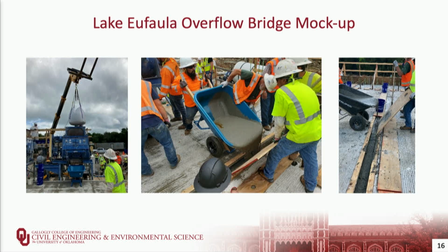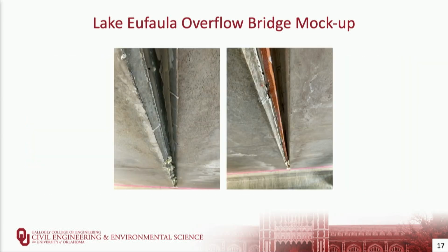For the mock-up, they used 2 horizontal axis high shear mixers and a proprietary UHPC material. They placed the UHPC into the joints just using wheelbarrows and some pieces of plywood as a backer to catch the material as it was cast into the joints. You can see on the right side picture, there are some 5-gallon buckets that are being used to provide a head on top of the UHPC as it's curing.